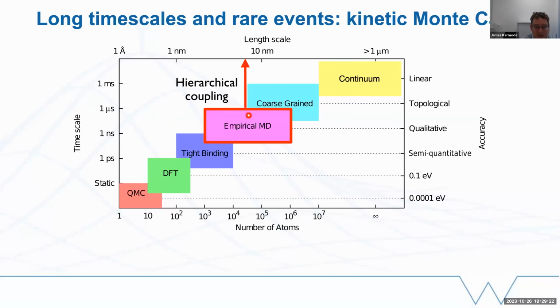So you could take out energy barriers or rates from these kinds of calculations and use them to do something like kinetic Monte Carlo or exact analytical calculations, either using data from the interatomic potential or DFT data directly, or DFT-quality data from an accurate potential, to get up to very much longer timescales. So I think this is a nice combination of approaches.